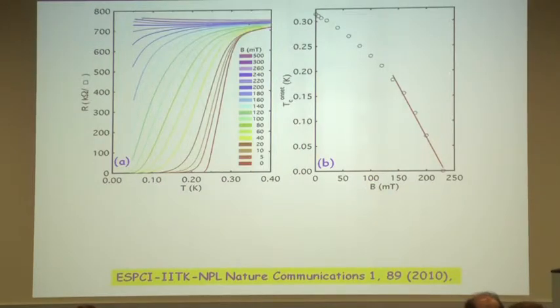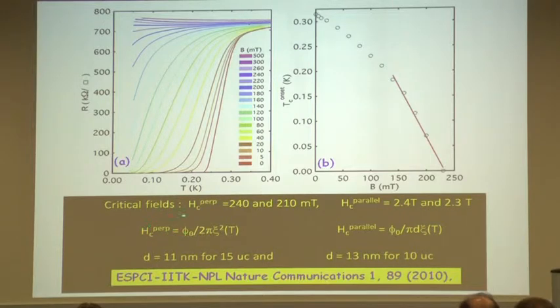One can extract the critical fields of this superconducting state. We have done these measurements by applying the magnetic field perpendicular to the plane as well as in the plane. So you have two critical fields, HC parallel and HC perpendicular. This is the formula for the perpendicular critical field. It goes as 1 over xi squared, the coherence length squared. And if I have the magnetic field in the plane, then one dimension is limited by the thickness of this 2D layer, so you have d times the coherence length. If I measure this and I measure this, I can extract my d. And that d comes out to be roughly about 12 to 15 nanometers. So that is the thickness of my two-dimensional superconductor at the interface.